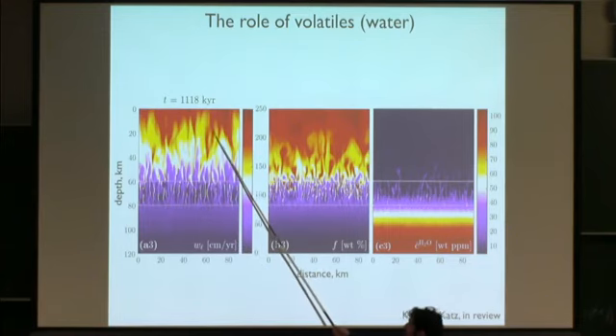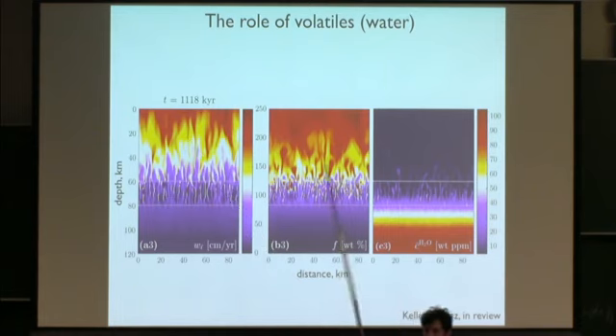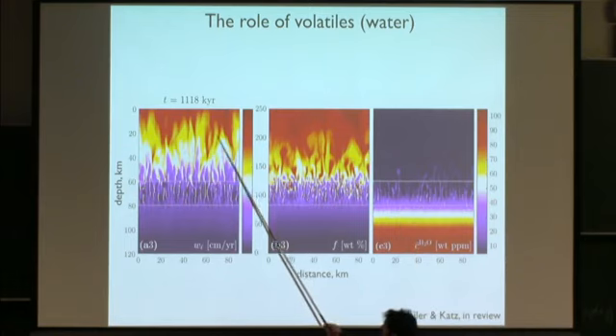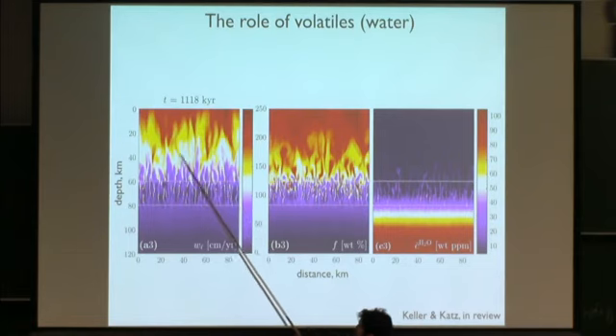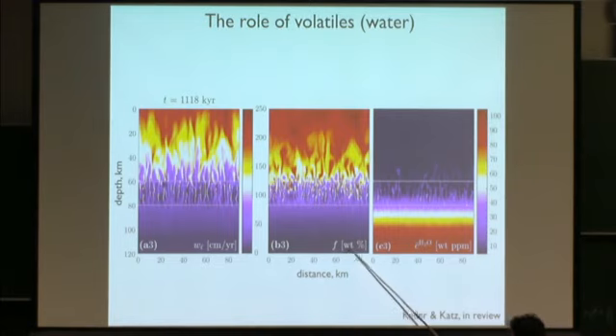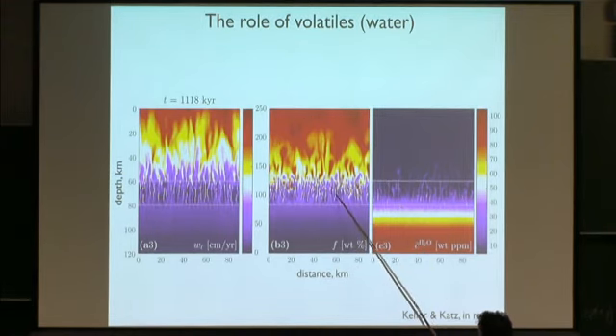The reason that it fades out is simply because we haven't attempted to include the solubility gradient of silicate in this part. So this part of the domain is not reactive. This is the reactive part where the volatiles drive enhanced melting. This is weight percent going from about 1% in the dark colors to 0, and so you can see that porosities or melt fractions are higher in these channels. And then this is the water content in weight ppm, so you see that we've injected about 100 weight ppm, not very much, into the bottom of the domain.